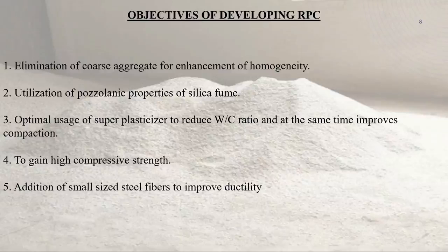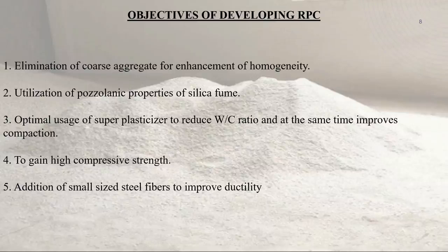Now we will discuss about the objectives of developing RPC. The objectives are as follows: elimination of coarse aggregate for enhancement of homogeneity; utilization of pozzolanic properties of silica fumes; optimal usage of super plasticizer to reduce water-cement ratio and at the same time improve compaction to gain high compressive strength; and addition of small sized steel fibers to improve ductility.